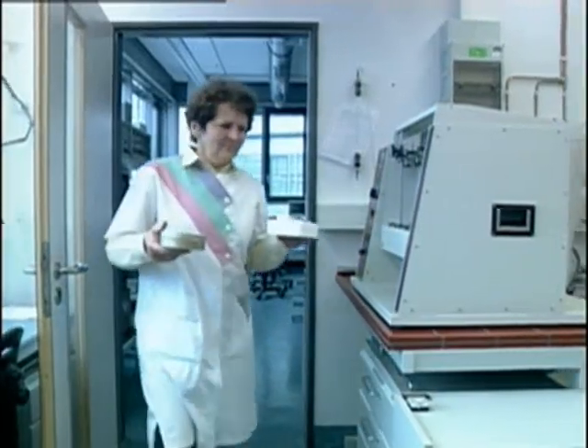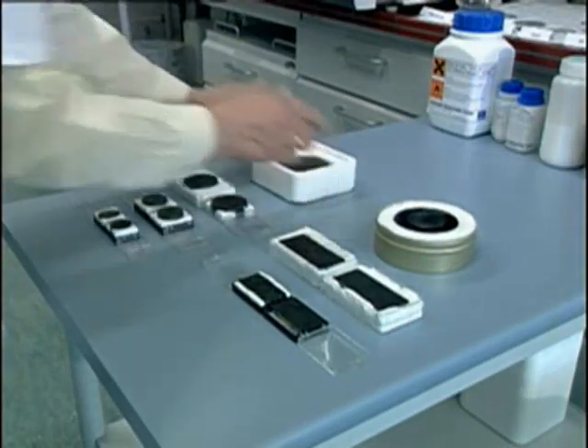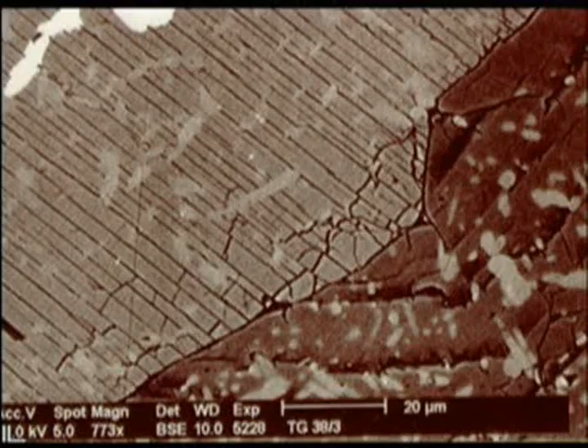The special magnetic quality of superconductors is determined by the size of single crystals. Therefore scientists make a big effort to grow single crystals as large as possible. But it's not a simple task to make large single crystals of yttrium-barium-copper oxide, as grain boundaries would interrupt the superconducting current flow. At a grain boundary, the superconducting current flow cannot cross into the adjacent grain.